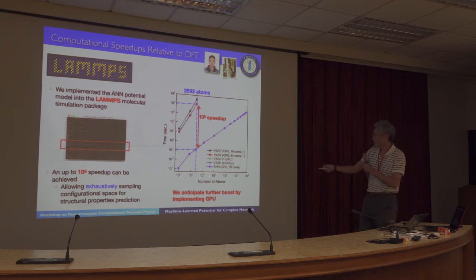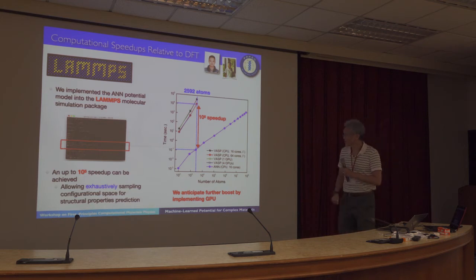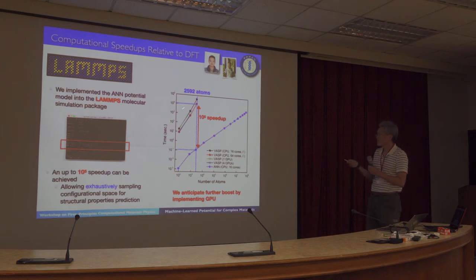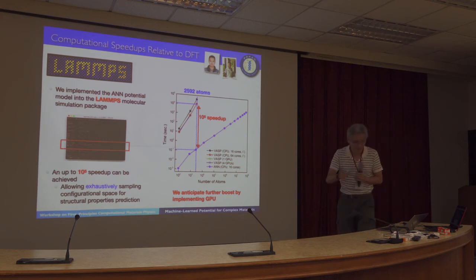And you can compare for a system of almost 2,600 atoms, using the neural network potential model, it's only slightly longer than 0.1 second. And this is only on 16 cores. And for VASP, it takes more than 3 hours. So this shows that by using neural network energy models, we have the possibility to sample the configurational or permutation space for complex materials in an exhaustive manner.